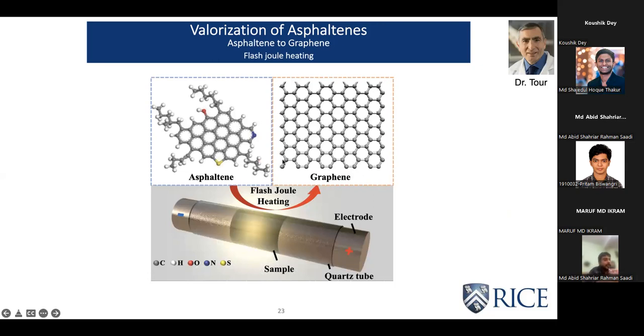Basically, you put the precursors in between two metal electrodes, which is enclosed in a glass cylinder, and you apply a very high voltage, around 200 to 300 volts. It depends on the material, but within less than 1 second, within a couple of milliseconds, your precursor is converted into these graphene-like structures.